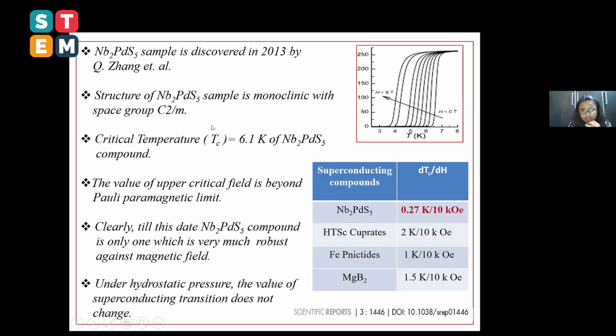In 2013. The structure of Nb2PdS5 is monoclinic with space group C2/m. The critical transition temperature of Nb2PdS5 is 6.1 Kelvin. While the critical temperature of this compound is low, the value of the upper critical field is very high, which crosses the Pauli paramagnetic limit. Clearly, from this table, you can see that the decrement of Tc with magnetic field in Nb2PdS5, in comparison to other superconductors, is low. That is 0.27 Kelvin per 10 kilo-oersted. This reduction of Tc with magnetic field is low in Nb2PdS5, which suggests robust behavior of Nb2PdS5 against magnetic field.